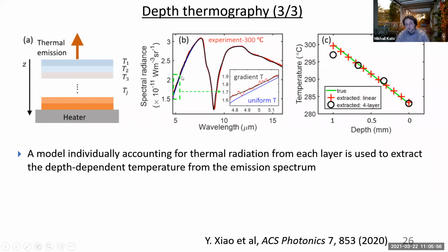But actually, if you zoom in to this region over here, where the wafer is expected to be semi-transparent to infrared light, you see that they're not actually on top of each other. The uniform temperature sample has a little bit less spectral radiance, and essentially that implies that there is some part of the object which is at a lower temperature than what we think it is.